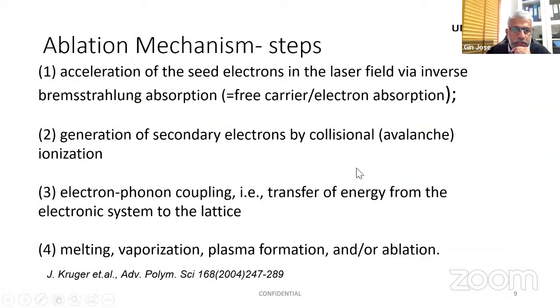So in short, we can describe the ablation mechanism in steps. You have the acceleration of seed electrons by the laser field through inverse Bremsstrahlung absorption, basically equal to free carrier and electron absorption. Then there is a generation of secondary electrons by collision. These few electrons already produced then create more electrons by collision, which leads to ionization. Then there is the process of electron-phonon coupling, that is, energy from the electrons is transferred onto the lattice. That also leads to the breaking down of the lattice, which ultimately leads to melting, vaporization, plasma formation, and what is generally called laser ablation of the material.